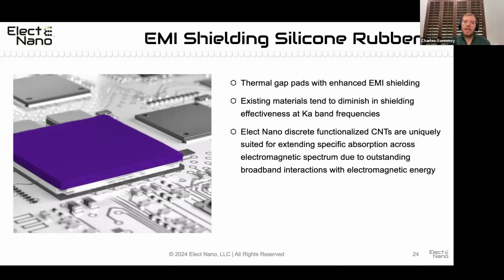And then particularly for the next generation of communications in the Ka microwave bands, that's proposed for 5G communications. And it's used for military and satellite communications a lot. But one of the things that we became aware of is that traditional EMI materials like ferrites have been designed to work well in our traditional 1 to 10 gigahertz range. But the absorption characteristics of those materials tend to drop off rapidly at higher frequencies, or you can pick one or the other, but you don't have the ability to make a broadband high performance EMI system.